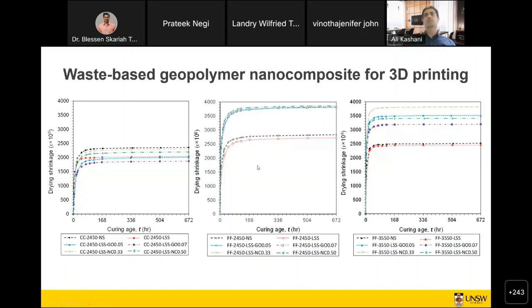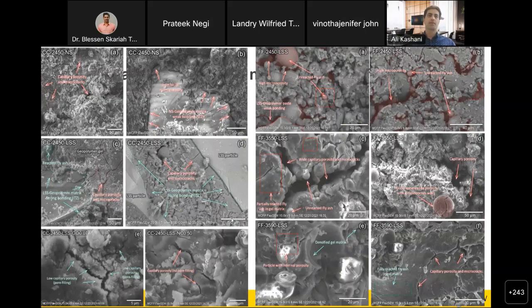So again, if we put the samples outside of the form, outside of the mold, you can see different conditions happening. Those nanomaterials are not very helpful in terms of mitigation of the dry shrinkage. As you can see here, in the free-form condition, addition of those nanomaterials actually exaggerates the drying shrinkage of the samples. The reason for that, as you can see in these SEM images, where the left two columns are for normal curing condition and the right two columns are the free-form condition, is that in free-form condition you can see a lot of unreacted material, a lot of microporosity, capillary porosity, and all of that is because of the underhydration and the water evaporation at very early stages, which contributed to high drying shrinkage.